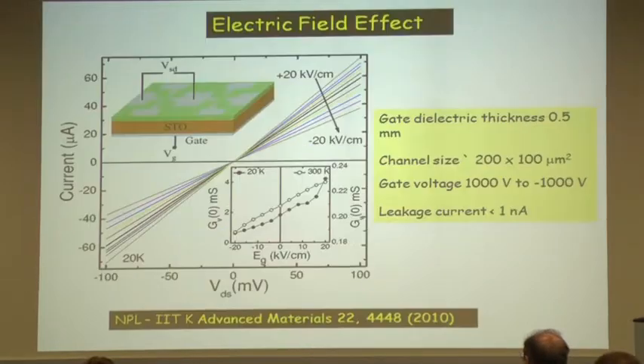So if I have a metal, you can see there is a very high density of states in the denominator. The Thomas Fermi screening length is only 2-3 angstroms. On the other hand, if I take strontium titanate, it can be several nanometers, even 100 nanometers. So it becomes a very important tuning parameter.